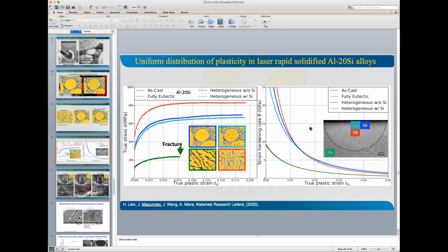Okay. And did you use bright field or dark field to identify the different grains? So we have used all kinds of imaging. A lot of what works is the Z contrast imaging, so high angle annular dark field to see composition contrast, and then high resolution imaging, and the HAADF images have been very helpful. Okay, thank you.